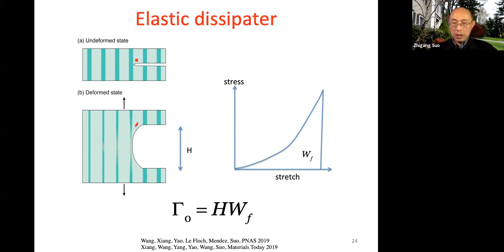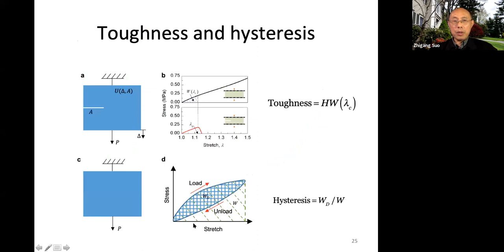So how enormous? We did a measurement. I already told you how we measure toughness, how we measure hysteresis. In particular, we're going to report hysteresis as a ratio: this hysteresis loop area WD, divided by the entire area under this loading curve, W. So when this number is 0, you have no hysteresis. These two curves, loading and unloading, match. This is purely elastic. If this number is 1, it's like metal. Natural rubber is somewhere in between. For polyacrylamide, it's less than 10%.